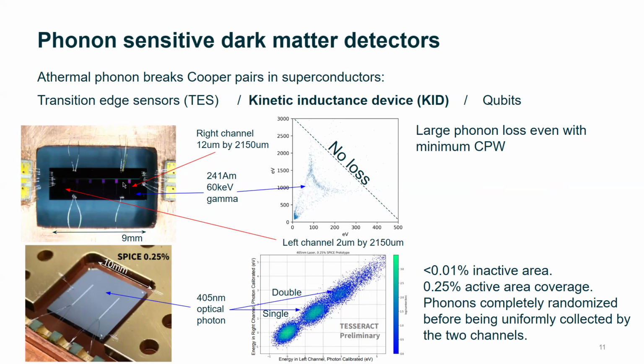This is simply because you have all the other areas. Although I removed the ground plane, you still have the area from the feed line. This is still a small fraction, but you saw this big loss. You see the phonon loss from the feature where the energy dependence has this curvature. If there's no loss, then you should see a straight line of the energy sharing between the two channels.